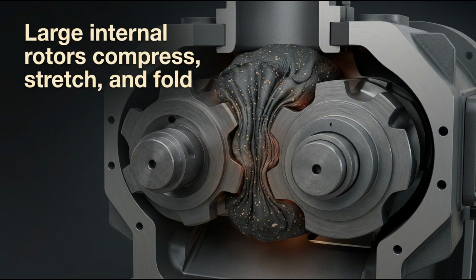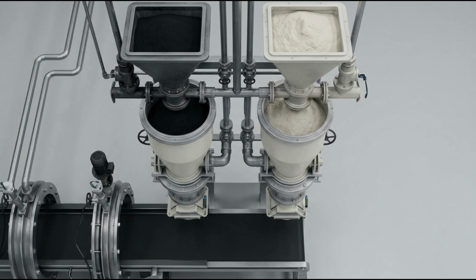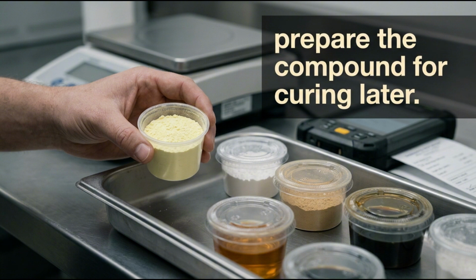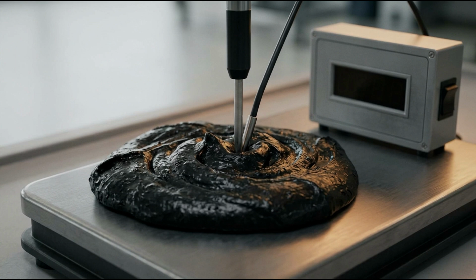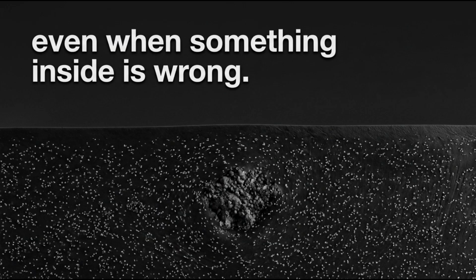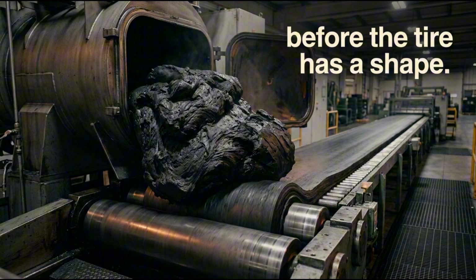Carbon black can reinforce rubber, improve resistance to wear, and contribute to its familiar black color. Silica is used in many tread formulations to help engineers balance wet grip, wear, and rolling resistance. Oils and resins influence processing and performance. Sulfur, zinc oxide, accelerators, and related ingredients prepare the compound for curing later. The quantities, processing time, and temperature all matter. A batch can look uniformly black even when something inside is wrong. A poorly dispersed filler or an incorrect ingredient level may affect how the finished tire wears, bonds, flexes, or generates heat. The first serious quality risk therefore appears before the tire has a shape.